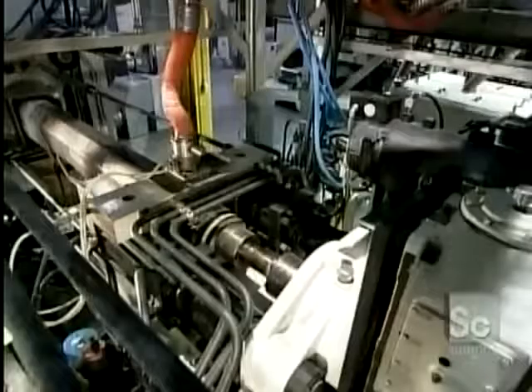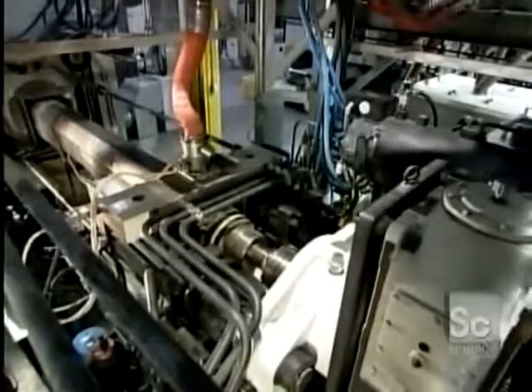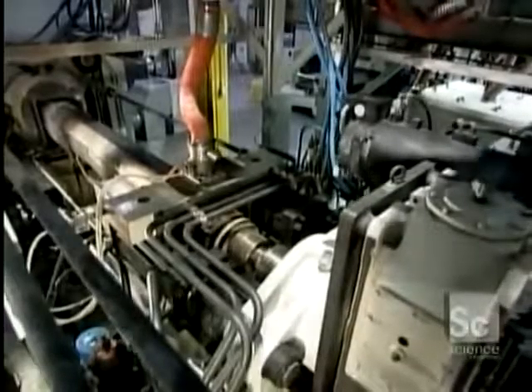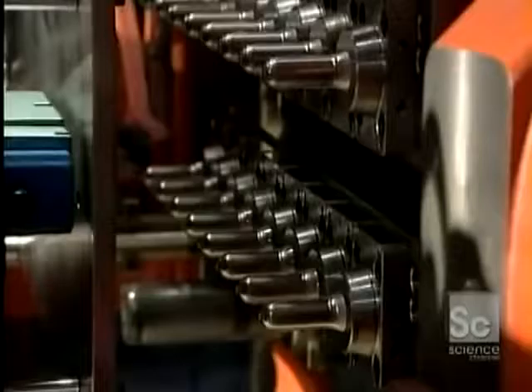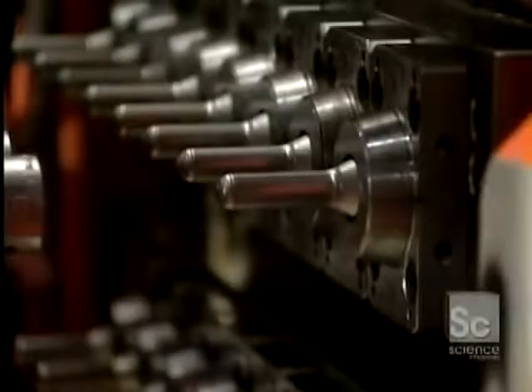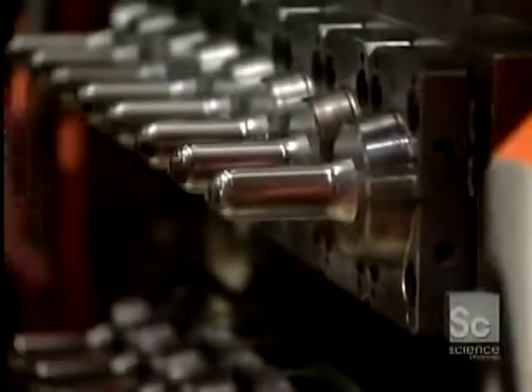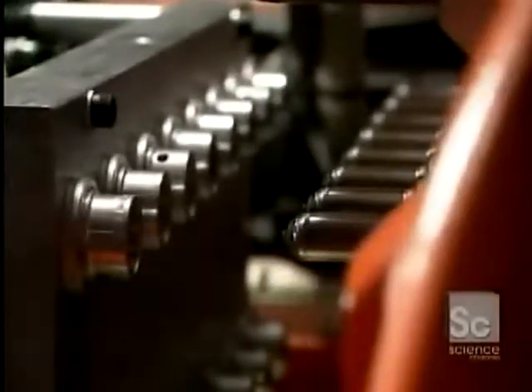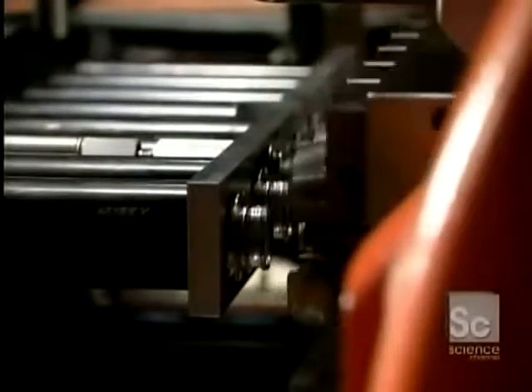The PET drops from the mixer into a plastic injection machine that heats it to a piping 600 degrees Fahrenheit. The dry, raw material melts into thick and gooey liquid plastic. The machine then shoots it at high pressure into a mold. This plastic injection molding process casts pieces of plastic called preforms — starter shapes that subsequent machines will transform into bottles or jars.